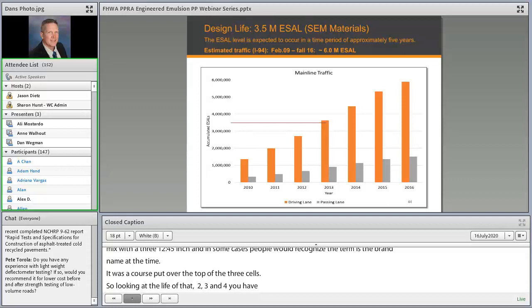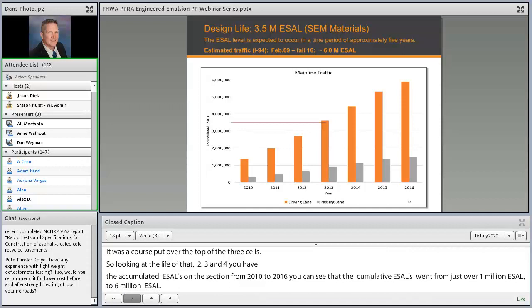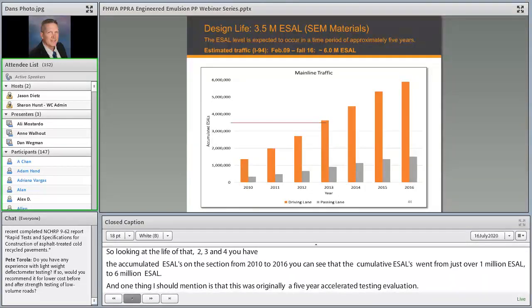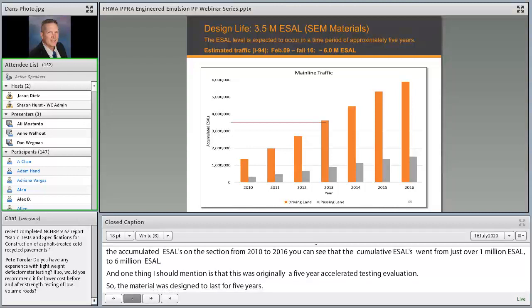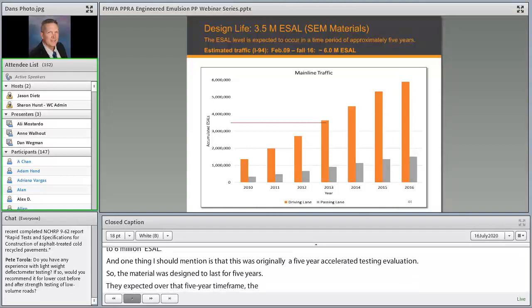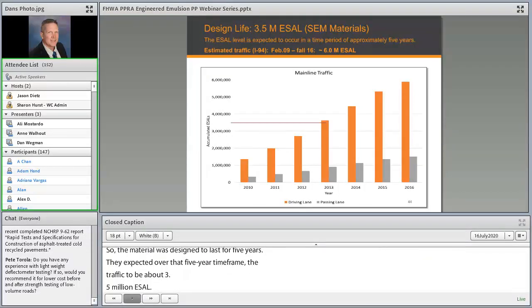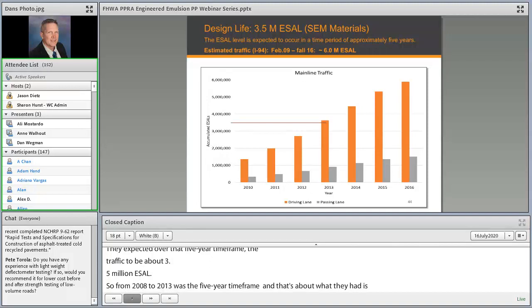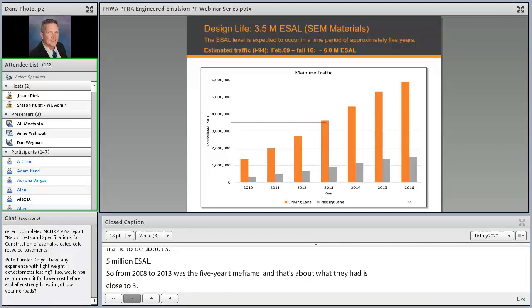One thing I should mention is that this was originally a 5-year accelerated testing evaluation. So the material was designed to last the 5 years, and they expected over that 5-year time frame for the traffic to be about 3.5 million ESALs. So from 2008 to 2013 was the 5-year time frame, and that's about what they had, as close to that 3.5 million ESALs. But because the roadway basically had no cracking, no distresses whatsoever, they elected to let it go. And in this slide, it shows that the traffic level has doubled and it's still performing extremely well.